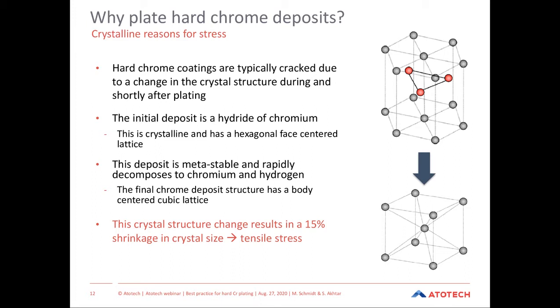So what tends to happen during plating is that we plate a chromium hydride layer. And this is crystalline and has a hexagonal face-centered lattice. And you can see the inclusion of the hydrogen atoms if we look at the structure on the top right-hand corner of the slide. And this structure is very unstable. And what tends to happen is that as we lose the hydrogen from the coating, this loss of hydrogen forces a change in the structure of the deposit.